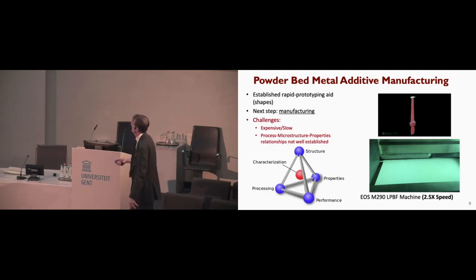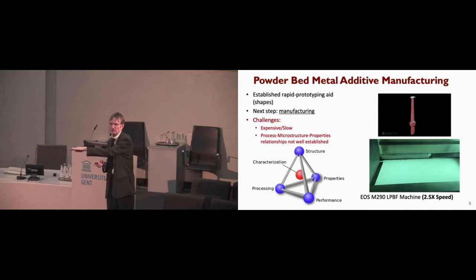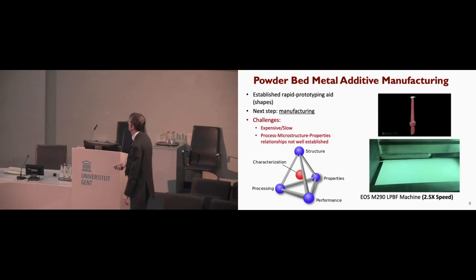So the destination here is to be able to apply what you might call the classical materials tetrahedron to understand the processing, so that you know well enough what structure you have, which in turn determines properties and therefore performance. But if you think about spreading more or less a human hair's worth of powder and then writing, you quickly realize that building a part of any significant dimensions takes hours and hours. In fact, for much of what we do, a typical print time might be 2 days or even 3 days. And that itself has some issues with it.